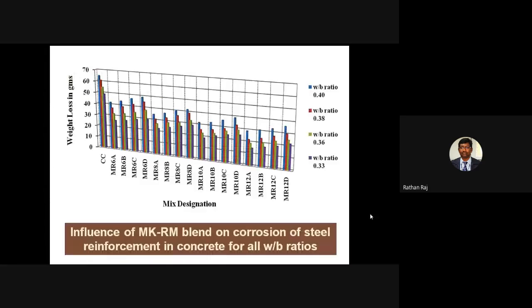The combination also shows some reduction in the percentage of losses in value, which shows that when we use the metakaolin and red mud in the combination of 50:50 or 80:20, in all the combinations it shows the superior property of corrosion resistance in terms of loss in weight; the percentage of loss in weight is very less in amount.